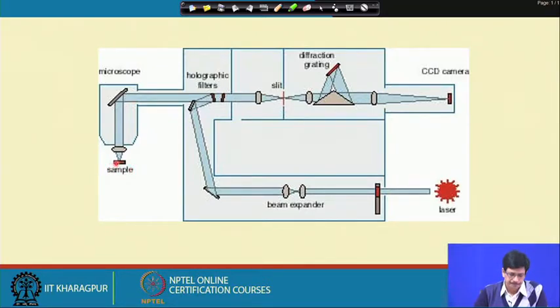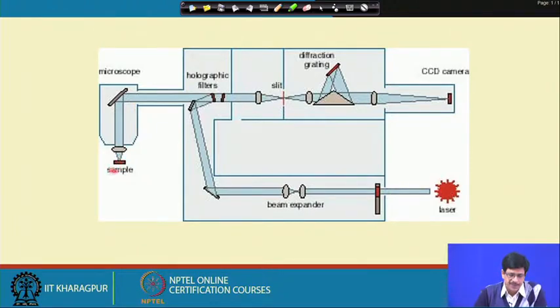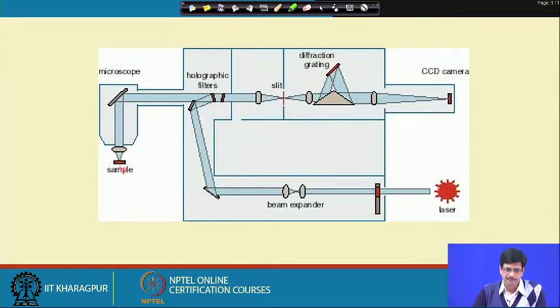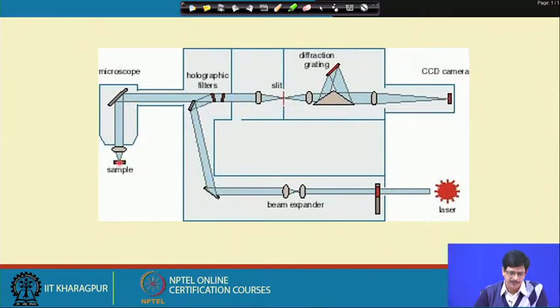Since inelastic scattering is very weak, we must be cautious about the depth at which we want information. An inclusion placed below about 550 microns from the surface may have its Raman signal attenuated or absorbed through the thickness of the wafer. Experience shows that inclusions within about 50 microns depth from the surface yield Raman signals that can be very effectively collected.